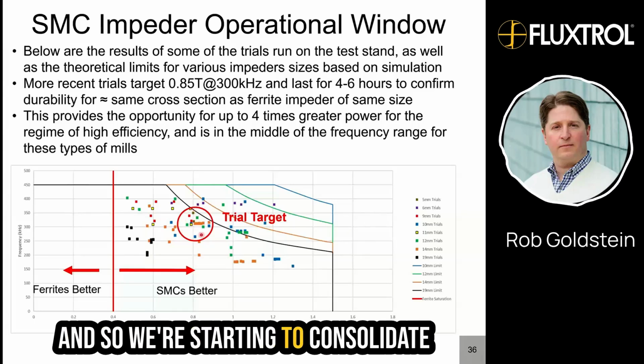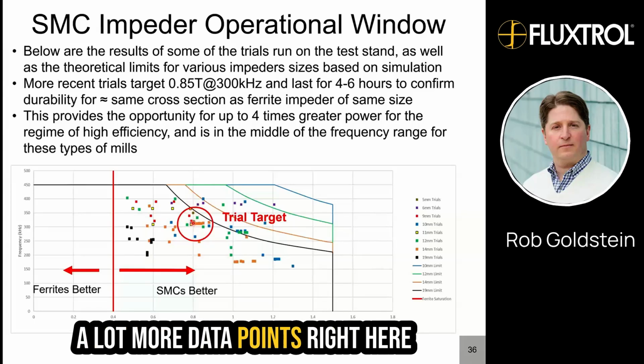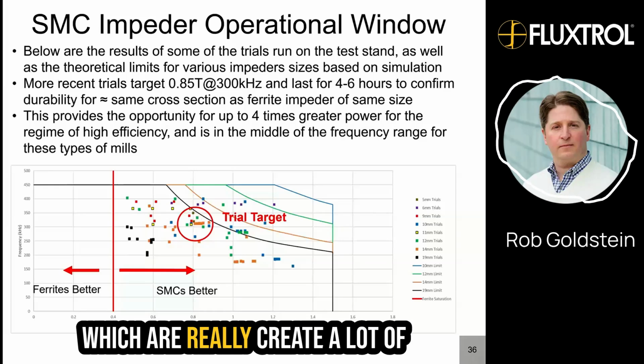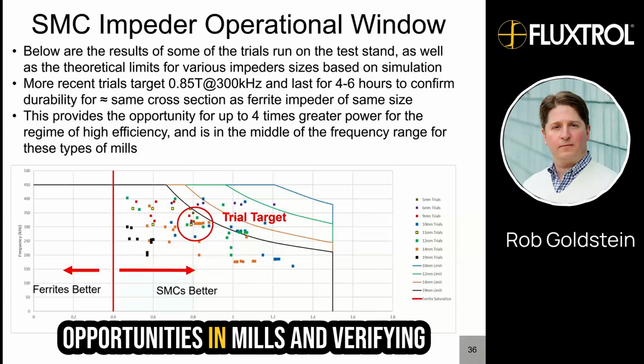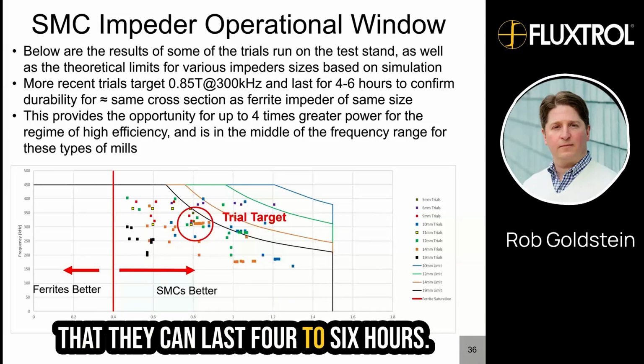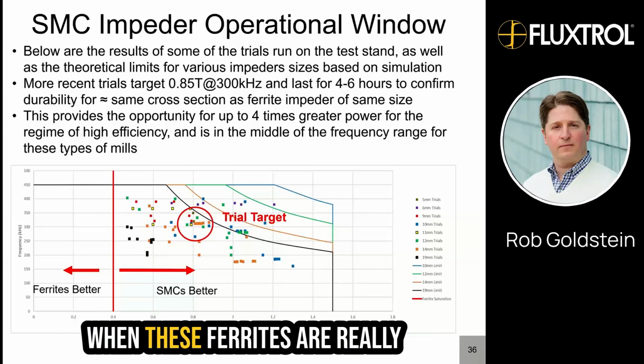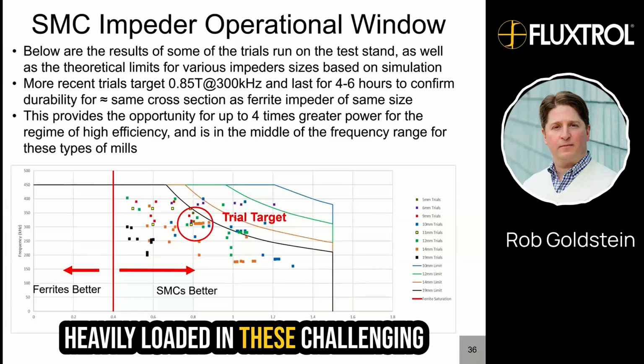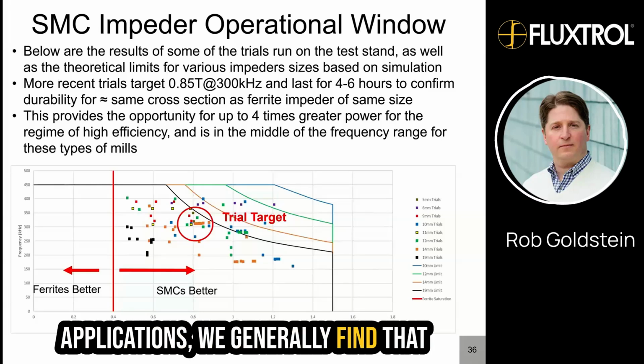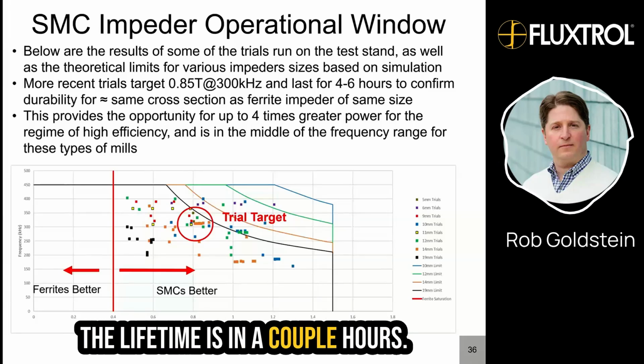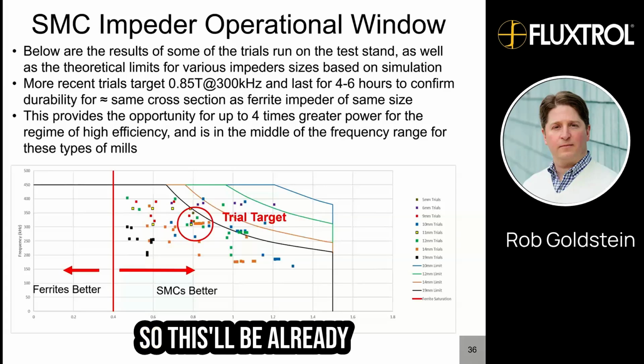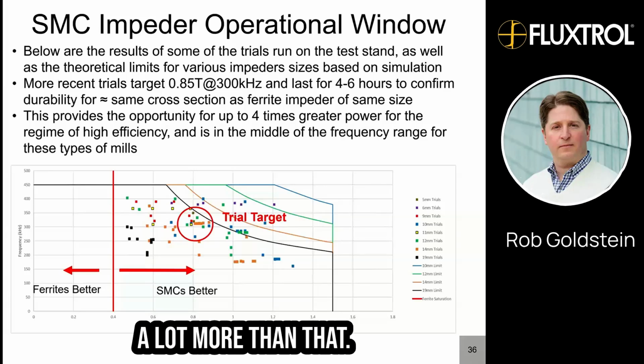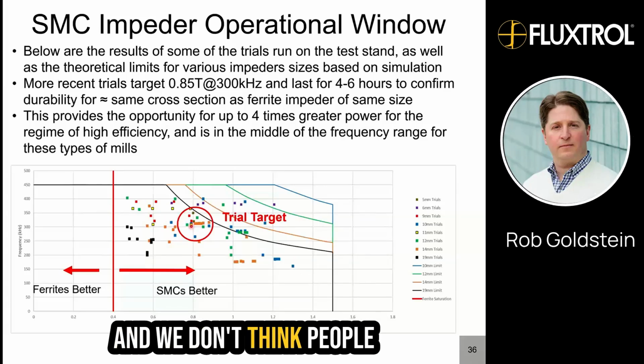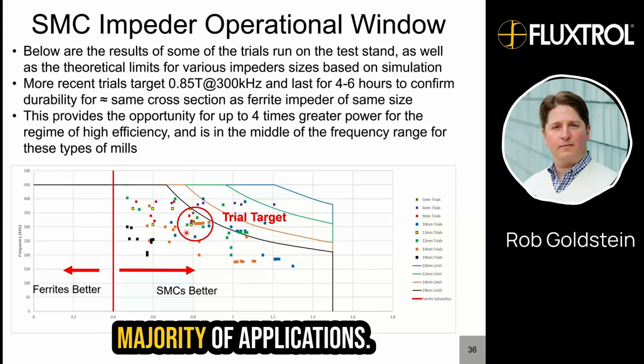And so we're starting to consolidate a lot more data points right here, which really create a lot of opportunities in mills and verifying that they can last 4 to 6 hours. When these ferrites are really heavily loaded in these challenging applications, we generally find that the lifetime is in a couple hours. So this will be already a lot more than that, and we don't think people can really get to here in the majority of applications.